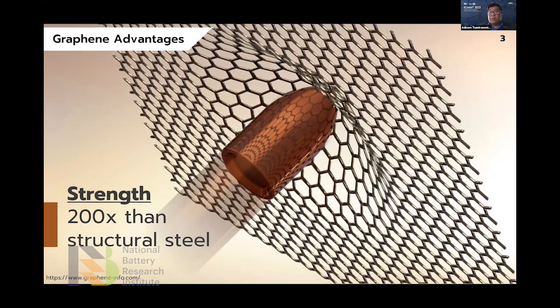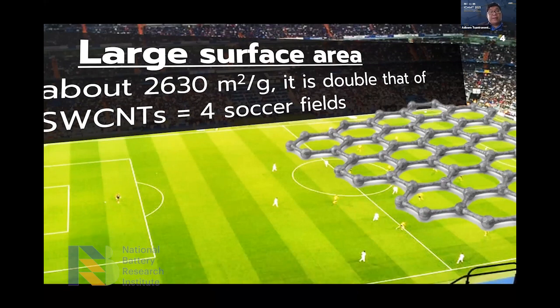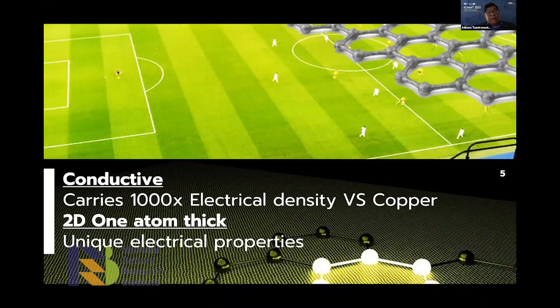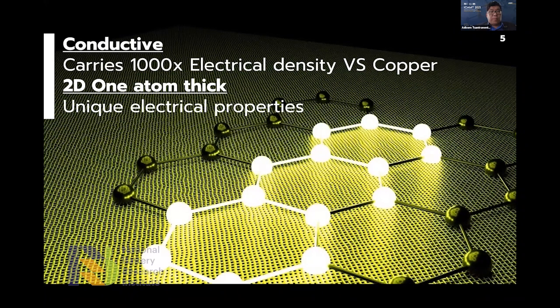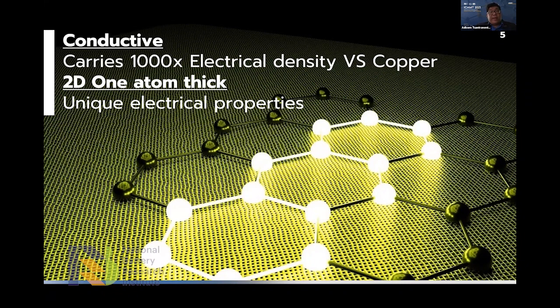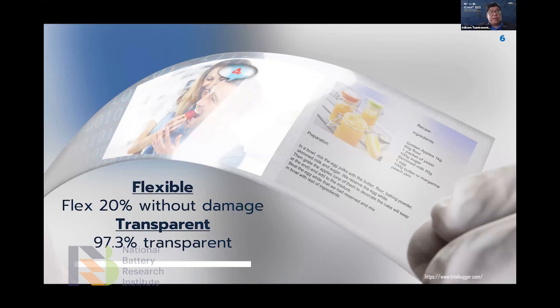Also, it has a large surface area, about double that of single-wall carbon nanotubes, about 2,630 square meters per gram, or about four soccer fields. It also has really good conductivity. It can carry more than 1,000 times the electrical current density of copper. It also has many unique two-dimensional electrical properties related to quantum effects on the surface of the graphene. Because graphene is a very thin layer, only a single two-dimensional layer of carbon, it has a flexibility of up to 20% and a transparency of about 97.3%.